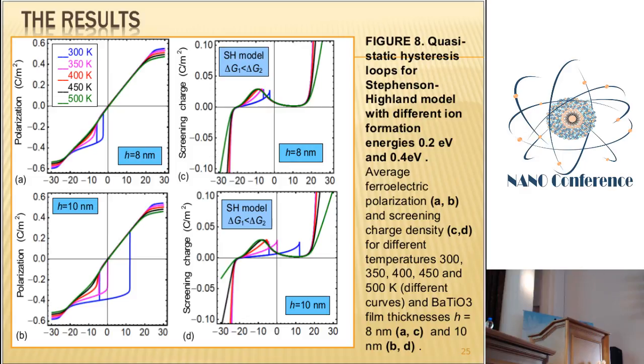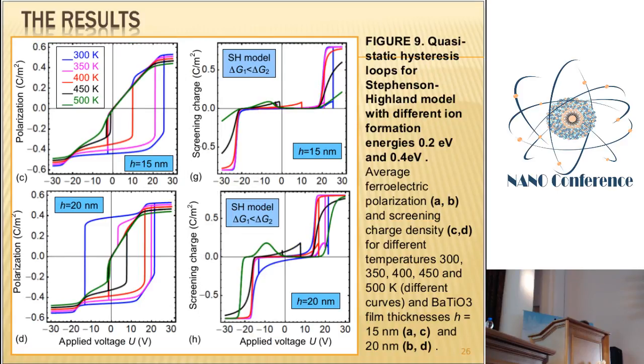Well, when you make these films a bit thicker, the effect becomes even larger. For example, for a 15 nanometer film, you have a pretty high coercive window at room temperature and a minor loop at 400 or even at 450 Kelvin. For a 20 nanometer film, you have an almost usual hysteresis loop at room temperature, except for this feature, an irregular loop at higher temperature, a minor loop at 400 and 450 Kelvin, and almost disappearing at 500 K.